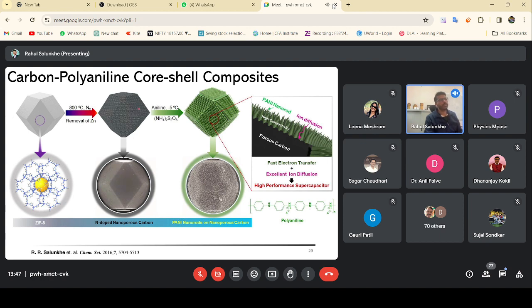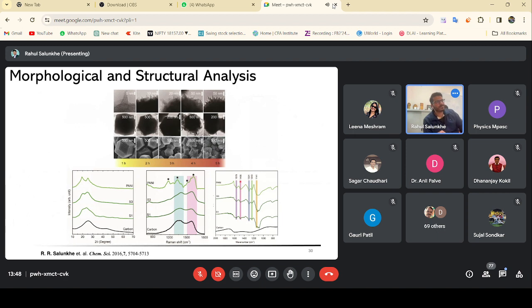So we have prepared this nanoporous carbon, and we try to coat it with the aniline monomer, and we try to develop a polyaniline. So polyaniline nanorods are grown on the surface of the material. As we can see from this SEM image, a very nice uniform coating of these polyaniline nanorods on the surface of the material is possible. Now the advantage is that these polyaniline nanorods have very high conductivity, and the backbone is a porous carbon for ion diffusion. So a fast electron transfer, excellent ion diffusion, and high performance for the supercapacitor can be realized by use of this kind of a structure.